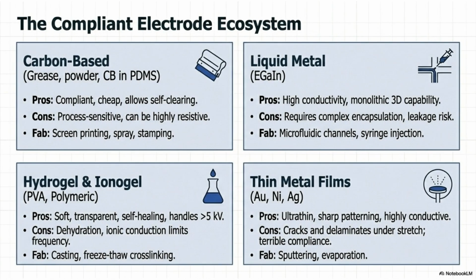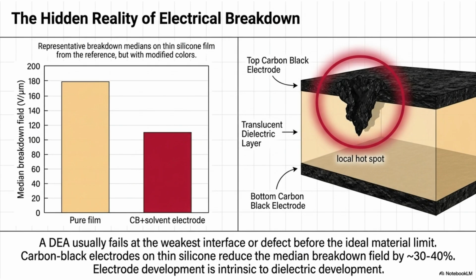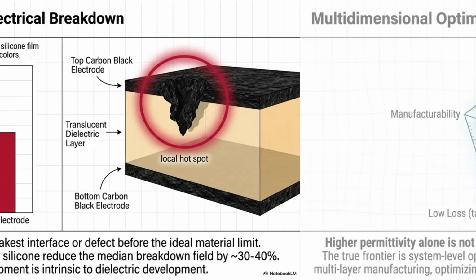The compliant electrode ecosystem includes carbon-based, liquid metal, hydrogel and ionogel, and thin metal films. Each option offers specific pros and cons regarding conductivity, compliance, processability, and fabrication complexity. Electrical breakdown often occurs at the weakest interface or defect in a dielectric elastomer actuator, not at the ideal material limit. Carbon black electrodes can reduce the median breakdown field by about 30 to 40% on thin silicone.